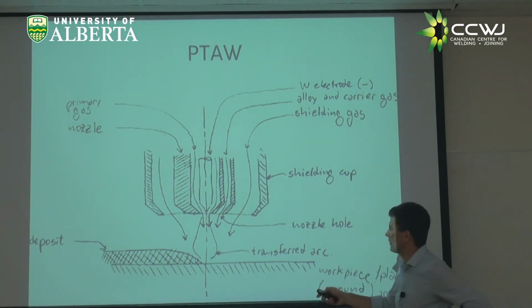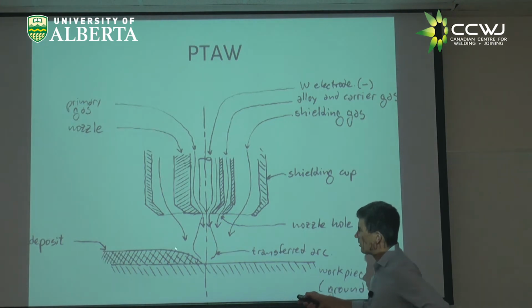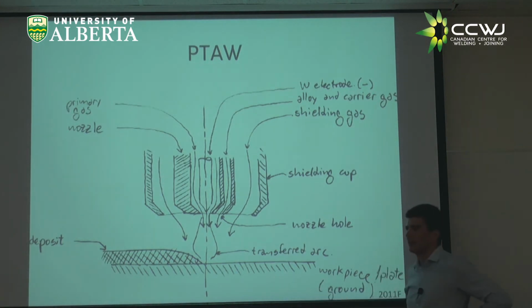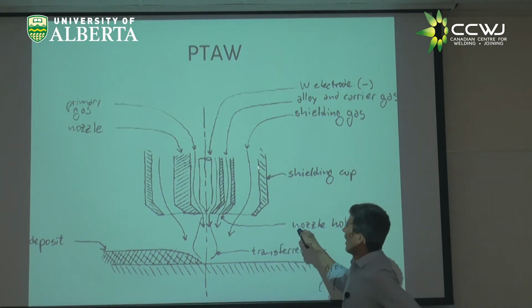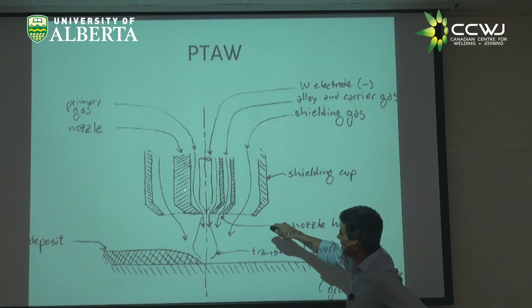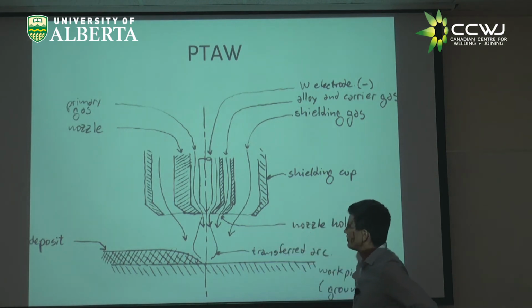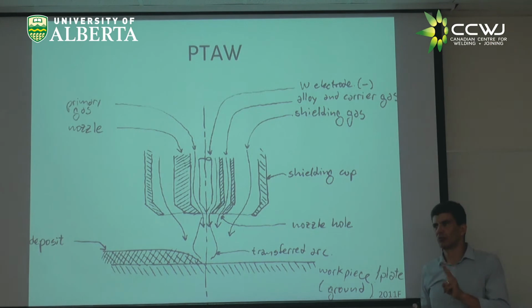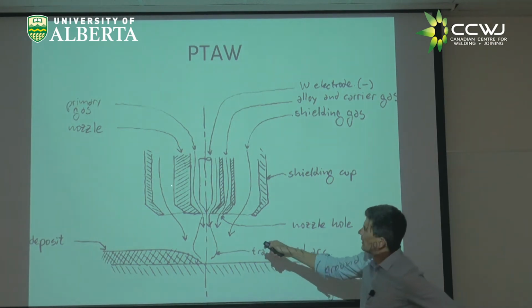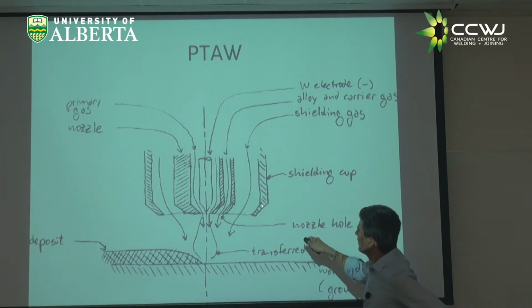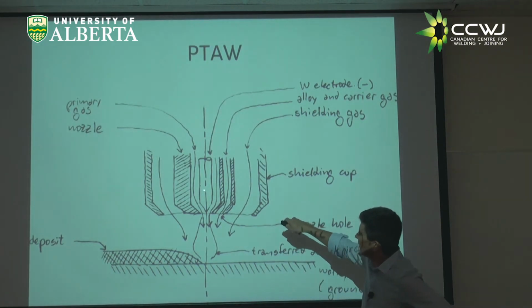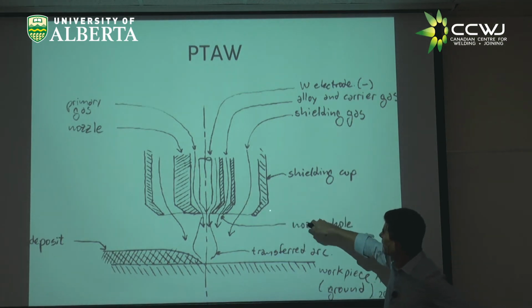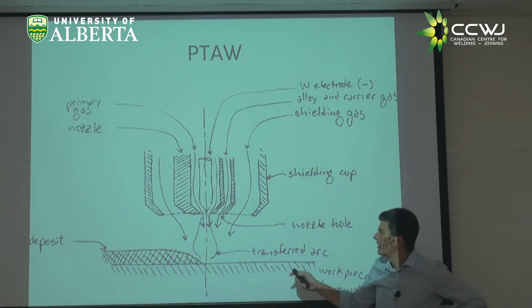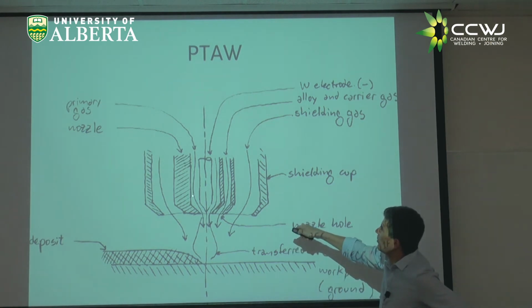We're going to give you a demo. Here's the plate. Same thing, and we have a weld pool, a deposit, and an arc. So far, so good. What is different? The torch is different. You see this part here? What we have now is at least 2 gas streams, right? We used to have 1 gas, that was the shielding gas. Now the shielding gas comes from here, same as before. So the TIG, the tungsten electrode, the shielding cup, we're fine. This is now a nozzle.